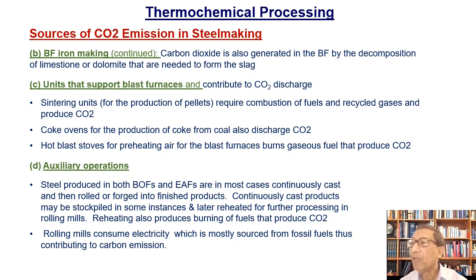And carbon dioxide is also generated by other reactions like decomposition of limestone. Limestone is calcium carbonate that upon heating produces calcium oxide that forms the slag, and carbon dioxide. And there are many units that support the blast furnaces that also contribute to the carbon dioxide discharge. Sintering units, for example, require combustion of fuels and recycled gases and produce CO2. Coke ovens, of course, burn some amount of coke and discharge CO2.